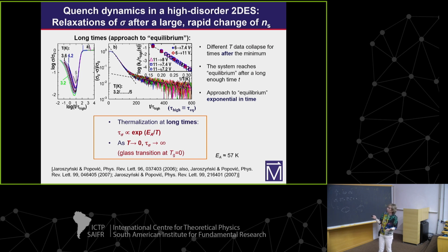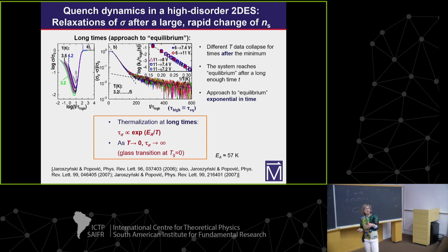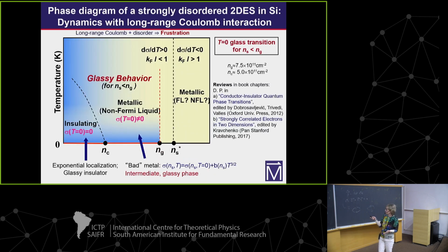And this obviously suggests that the glass transition is at zero temperature. This was done a long time ago, and in addition to this protocol, we also used other protocols, demonstrated aging, looked at the fluctuations and so on, and I will not be talking about that. This is all summarized in these book chapters.